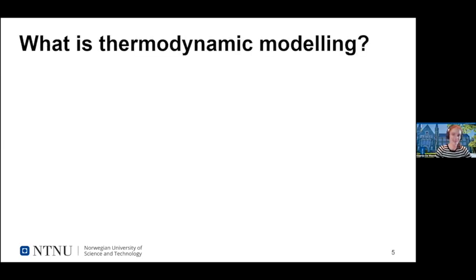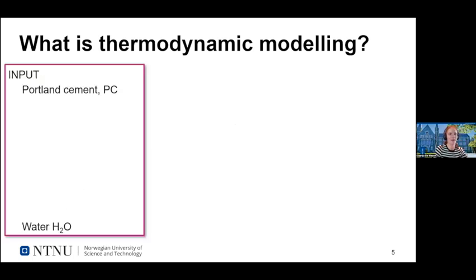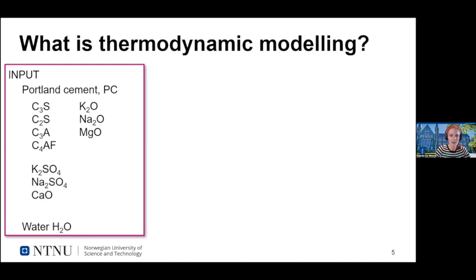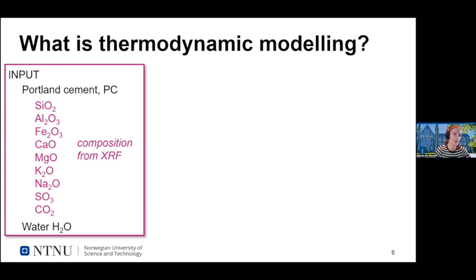So what is actually thermodynamic modeling in this context? What we normally do is gather input from your Portland cement, and you include some water because you're going to look at hydration. What you need from your Portland cement is your clinker phases, your oxides, alkali oxides, magnesium oxide, your sulfates, and maybe also your calcium carbonate. If you're not that lucky and you don't have the full characterization of your cement, you could also simply use your oxide composition, which you can get from XRF, which most cement producers provide.